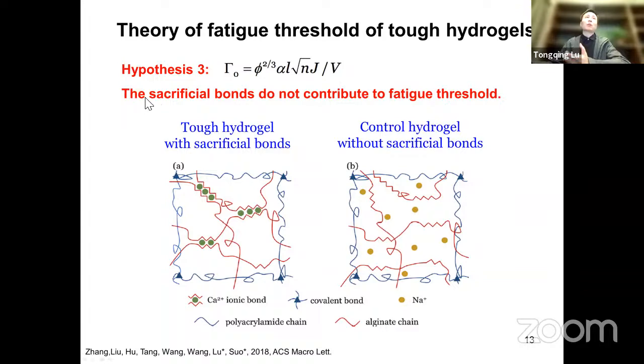Our first assumption is that the sacrificial bonds do not contribute to the fatigue threshold. To verify this, we prepare two kinds of hydrogels. One kind we call tough hydrogel with sacrificial bonds, because we introduce calcium bonds. The calcium bond can cross-link these red chains in the double network hydrogels. When you stretch or break these hydrogels, these sacrificial bonds will dissipate energy. As a comparison, we prepare another hydrogel without sacrificial bonds. Here we use sodium, which cannot cross-link these polymer chains. The only difference between these two kinds of hydrogels is the calcium or sodium ions.